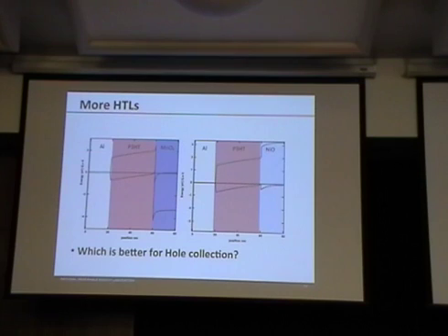That wouldn't be good. Now, to be fair, if I went to a system like PCD-TBT, where I could lower this, now the nickel oxide may be better than the moly, right? But just picking a P-type oxide isn't going to make the world perfect. We really do have to match these things up energetically, and we have to do some kind of accounting for all the different energetics in the system.